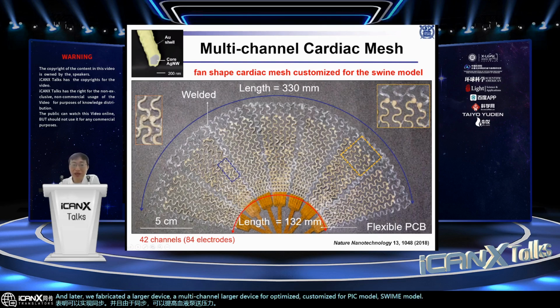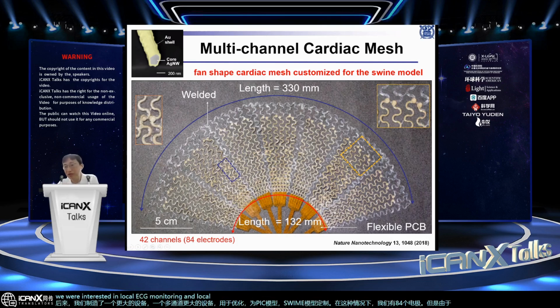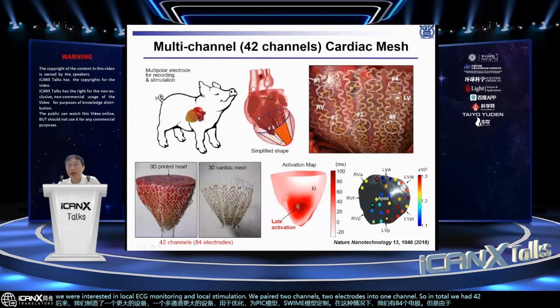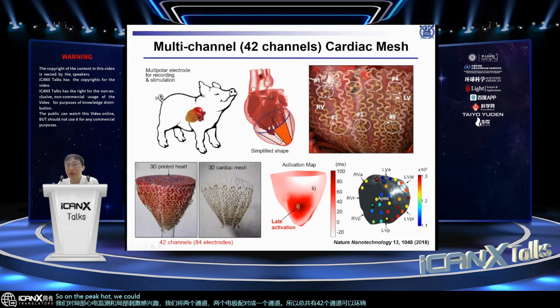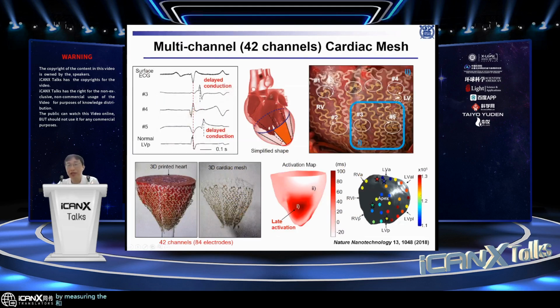In this case, we had 84 electrodes, but since we were interested in local ECG monitoring and local stimulation, we paired two electrodes into one channel. So in total, we had 42 channels that could wrap around the heart surface. On the beating heart, we could measure local EKG, and by measuring the local EKG, we could see the healthy part and the diseased part. Typically, the diseased part of the heart shows late, delayed conduction. So by making an activation map, the late activation part corresponds to the diseased part of the heart.